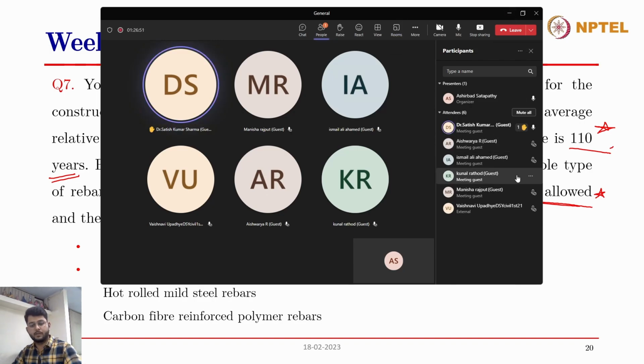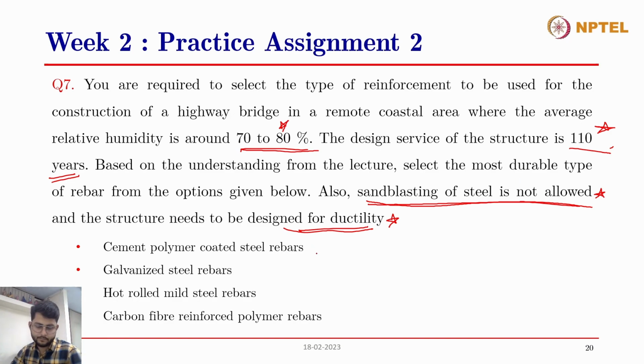Okay, cement polymer coated steel rebars will function properly only if you clean the surface properly. So sandblasting is not allowed. In that case, cement polymer coated steel rebars will not work. Then galvanized steel rebars, yes, as came out in the lecture also, its performance has been proven. This is the best type of material for this type of situation. Then the third one is hot rolled mild steel rebars. It will definitely corrode because it is a saline environment. And the last one is basically for strength, and again, you require good sticking power. So unless you clean the surface properly, it will not stick properly, and there will be delamination. So obviously, galvanized steel rebar will provide the best protection in this type of situation. Okay, thank you.